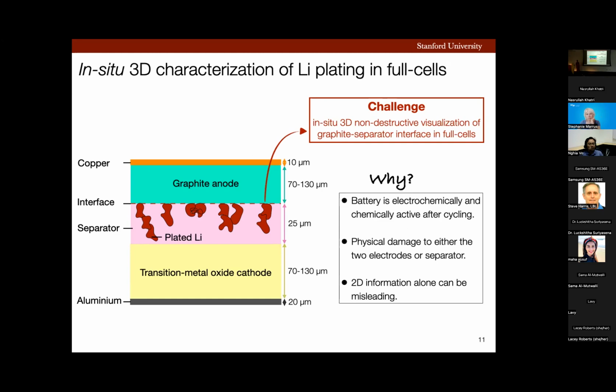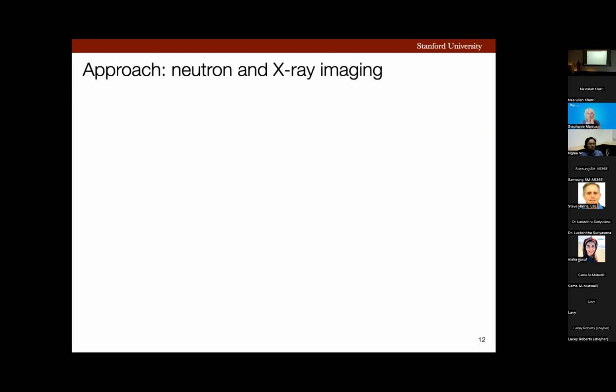Now, to address this challenge, my approach involved using non-destructive advanced neutron and X-ray imaging diagnostics. Neutron and X-ray 3D imaging is particularly advantageous for this work because of the way they interact with matter, which is encapsulated by this Beer-Lambert law. Here, I is the beam intensity through the sample, I naught is the incident beam intensity, t is the neutron and X-ray path length through the sample, and mu is the linear attenuation coefficient, which is a material property, which means this number would be different for different materials.